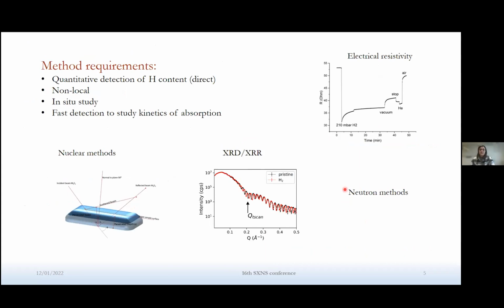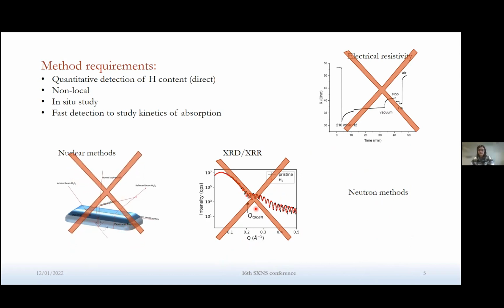So of course, there are several methods that can be used to detect hydrogen in thin films. The most used are electrical resistivity, X-ray scattering methods, NMR, nuclear methods, and of course, neutron methods. However, our ideal method of detection would be quantitative and direct in the sense that we do not need other calibrations to get the exact amount of hydrogen present. And so, for example, this is the case of resistivity and X-ray methods. But also we would like to be able to study in situ absorption and desorption processes. And this is not possible with the high energy ions used in nuclear methods. So basically we are left with neutron methods, and in particular, since we talk thin films, with neutron reflectometry.